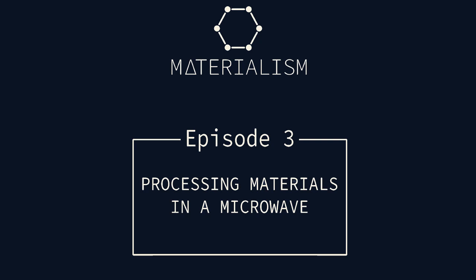In a hybrid model, you use a susceptor to absorb microwaves, and then you re-emit heat similar to a conventional oven. But you also have metals directly absorbing microwaves as well. Hybrid heating produces a much more homogeneous material where both core and surface are near the same temperature, and therefore they have a more desirable microstructure.